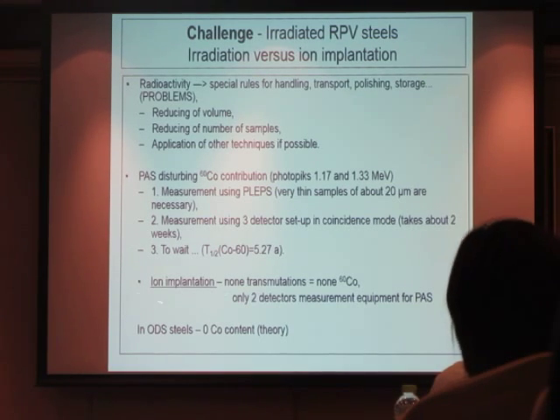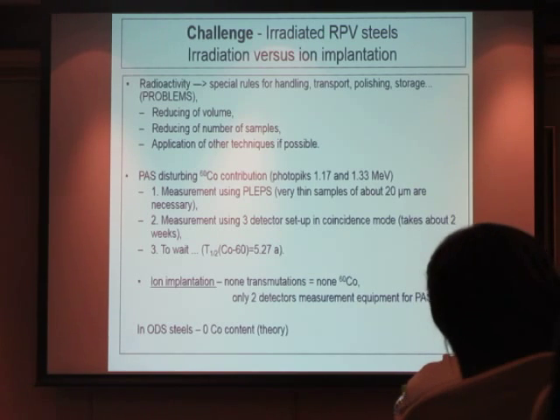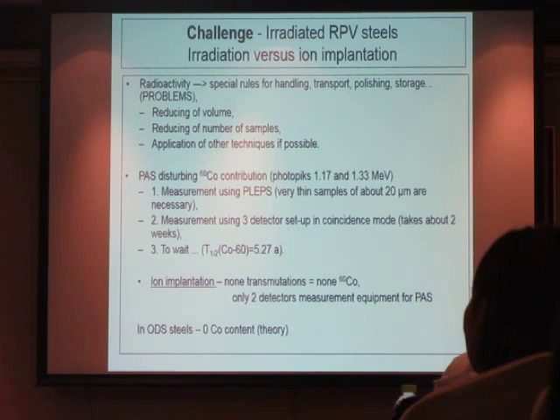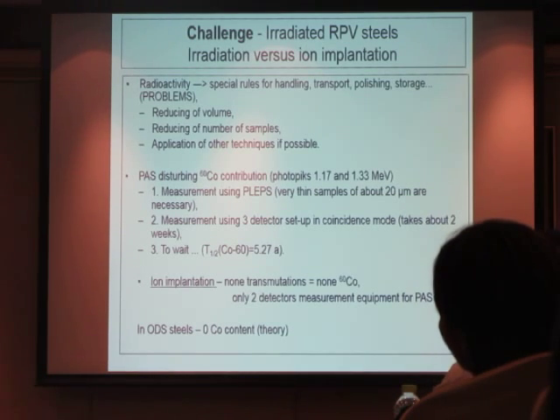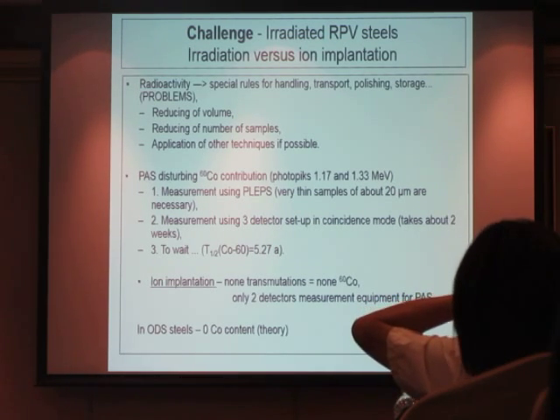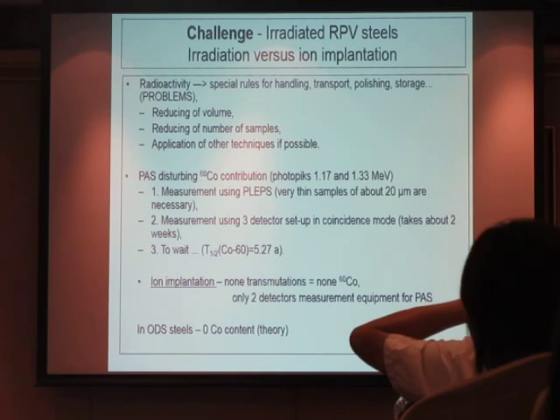Good. There is another way to make an experimental simulation of irradiation: by ion implantation. You can decide which type, and implantation by hydrogen ions seems to be, from the mechanical point of view, a good approach. Protons have a charge, neutrons have no charge. There is a difference. Nevertheless, the mass of neutrons and protons is the same. Therefore, these knocked-out atoms can be simulated by the implantation of protons, of hydrogen.